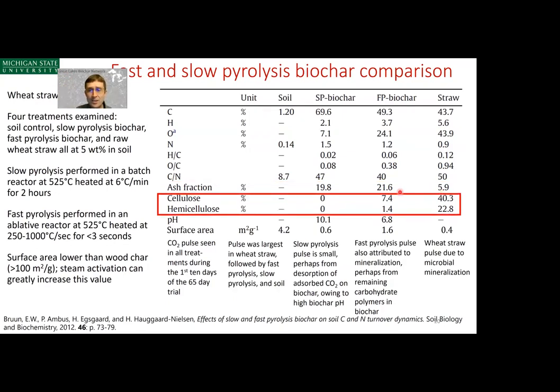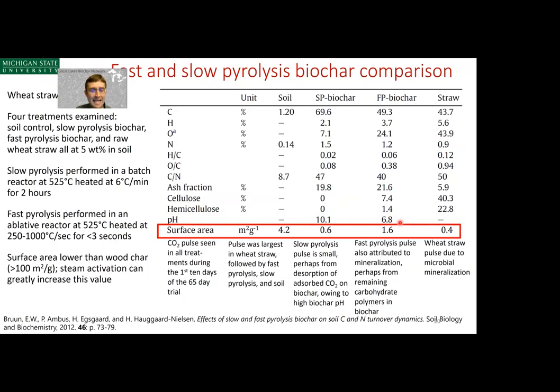Cellulose and hemicellulose do remain. There's a small amount of these carbohydrate polymers present in the fast pyrolysis biochar, but none present in the slow pyrolysis biochar. The pHs are different too. The pH of slow pyrolysis biochar is relatively high at 10.1, and about neutral for fast pyrolysis at 6.8. Interestingly, the surface areas aren't that high. We tend to think of biochars as having high surface area, but these surface areas are actually quite low from both of these processes, quite a bit lower than wood char pyrolysis, which is around 100 meters squared per gram.